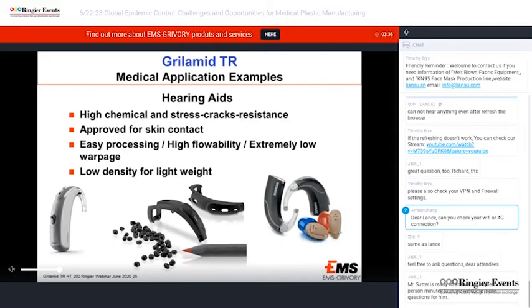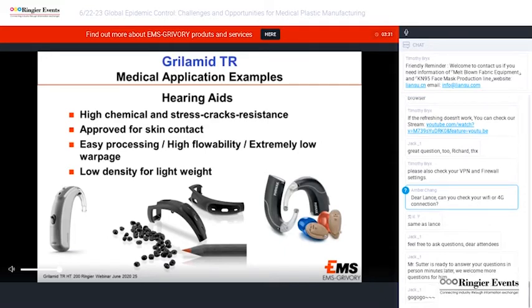Hearing aids is quite a sizable application for Grilamid TR. The reason why Grilamid TR is being used by several hearing aid manufacturers is due to its high chemical and stress crack resistance. Even chemicals such as skin moisturizers, perfumes, and hairsprays can cause issues for amorphous materials, but not for Grilamid TR. Approval for skin contact, easy processing, and high flowability, as well as low warpage due to the fact Grilamid TR is amorphous. Last but not least, it has low density, allowing for very light hearing aids, improving the comfort to the wearer.